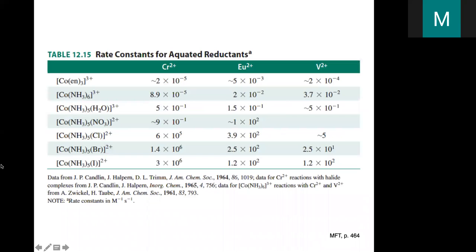Okay, so here are some data. These are reactions similar to the cobalt(III) chromium(II) inner sphere reaction we looked at previously. But all of these reactions involve cobalt(III) complexes, and the reductants can be chromium(II) aquated, europium(II) aquated, or vanadium(II) aquated. And you can see here the rate constants can vary widely. So here we're seeing 11 orders of magnitude difference for cobalt(III) being reduced by chromium(II). And you can see that the rate is really following very much whether or not there's a good bridge forming ligand on the cobalt center.